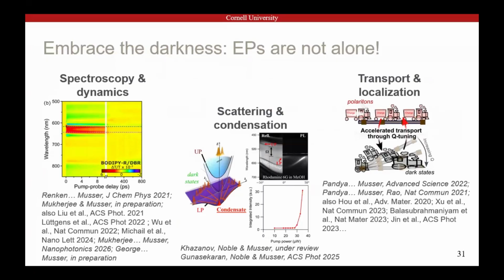They have lots of interesting properties like long-range transport, but they are not alone, and they are by far the minority in the cavity. They're swimming in a sea of dark states, and we have to understand the dark states to understand cavities. And this is known in many areas. For instance, polariton condensation is one of the coolest things that polaritons do, but you can only understand condensation by starting your system in a bunch of dark states that scatter into the lower polariton. But the interplay between polaritons and dark states also impacts the long-range transport that we and others have observed, and it ruins most spectroscopy experiments that we can do because they give rise to a whole sea of artifacts.